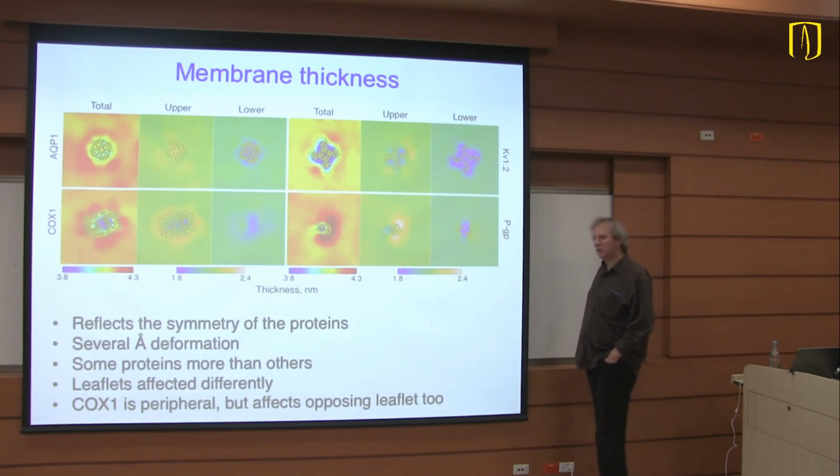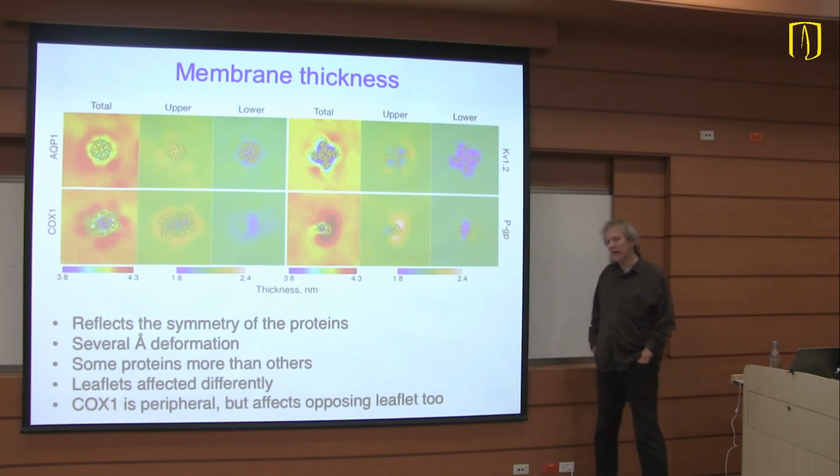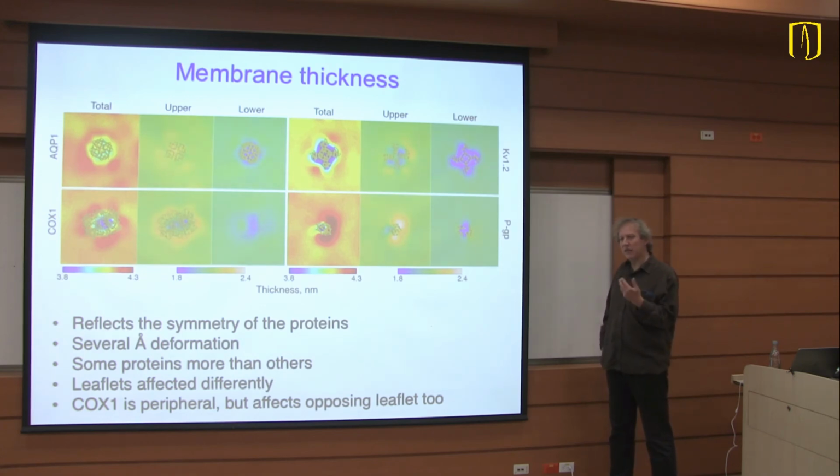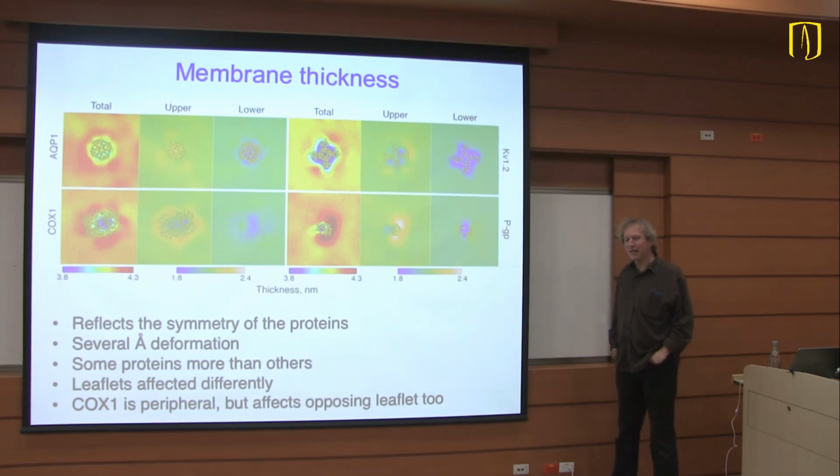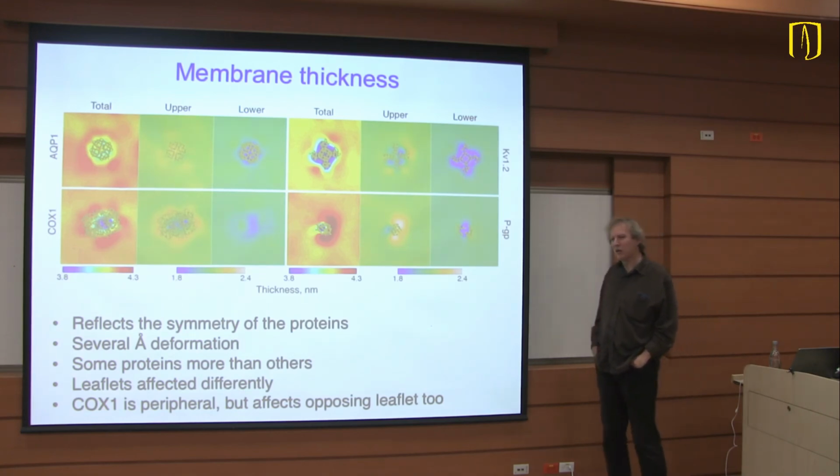Yeah, so that's not an obvious question. We use a combination of parameters to identify a local phase. It's based on order, the chain order. It's based on the neighbors. So if all of the neighbors are the same type, that makes it more likely to be a different phase. If all of them are randomly type A versus B, that means there is no local domain. And then there are some other parameters that you can tweak to try to identify this. There is no perfect solution for this that I know.